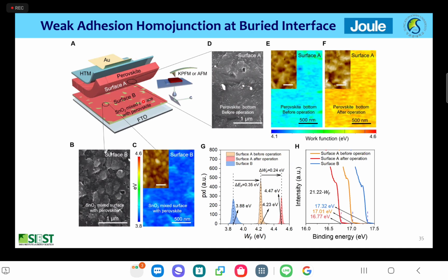And then recently we also found that the interface of this NIP structure, for instance, where we used the SnO2 layer and then the FA-based perovskite film, is pretty much weak. Then why is this interface weak? We detached the perovskite from the tin oxide, and found that some of the perovskite is still on the tin oxide layer. And then interestingly, we found that the work function of the perovskite is somewhere around 4.23 electron volt.